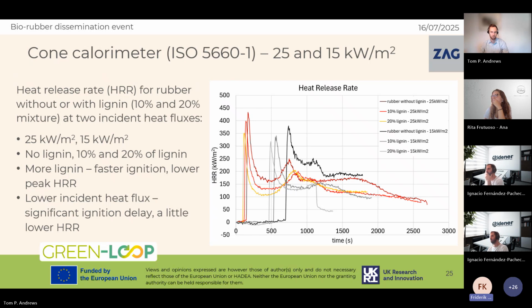So when we start measuring fire and fire properties, we first start with a cone calorimeter and the heat release rate. So here we have certain curves. What we see on these curves is that the lower the heat flux incident, the longer it takes to ignite. We can see that rubber without lignin, for example, ignited in approximately 700 seconds at 15 kilowatts, and at about 2 minutes at 25 kilowatts per square meter. And when we are adding lignin, we are actually making the ignition faster. But we're also making the heat release rate less violent, less intensive. So it's more spread.